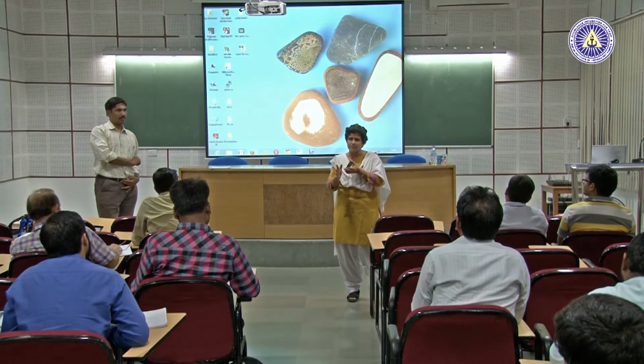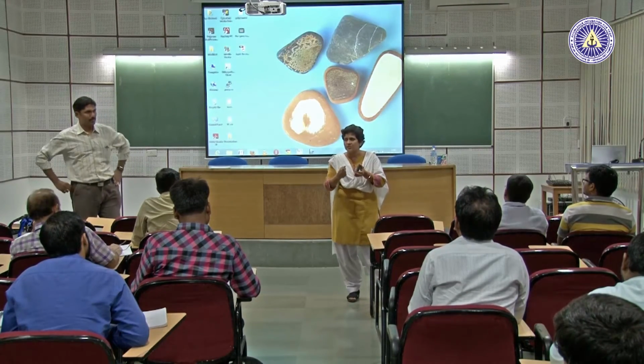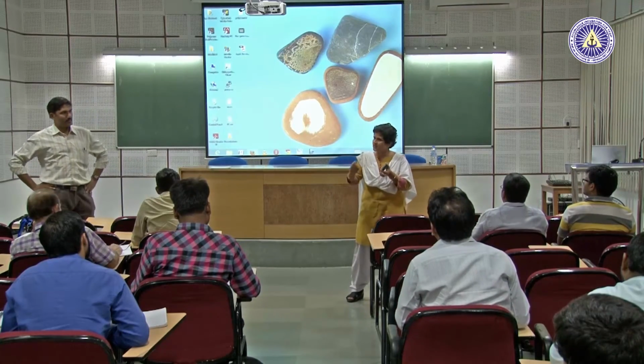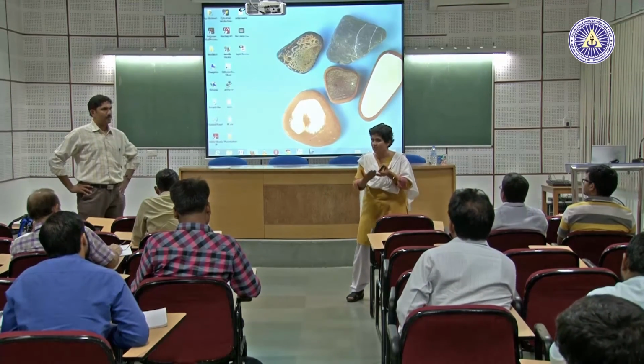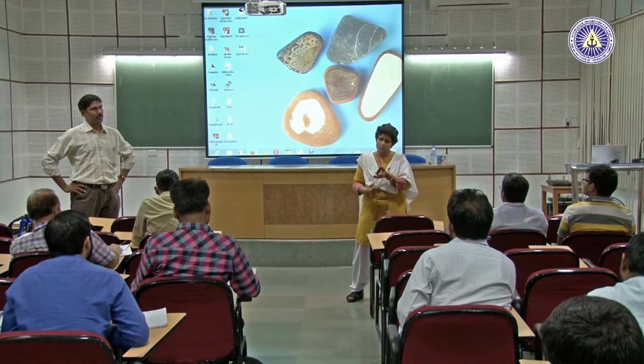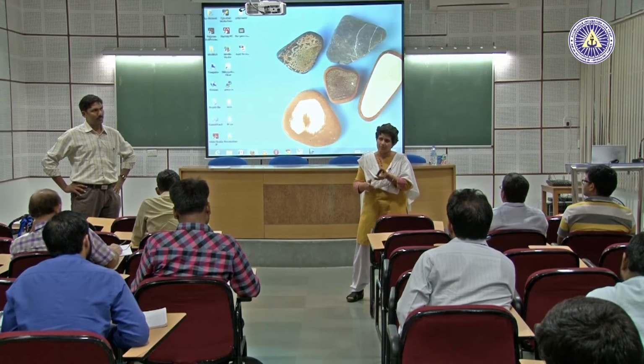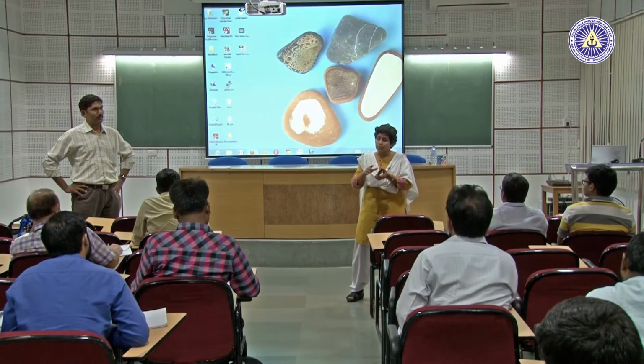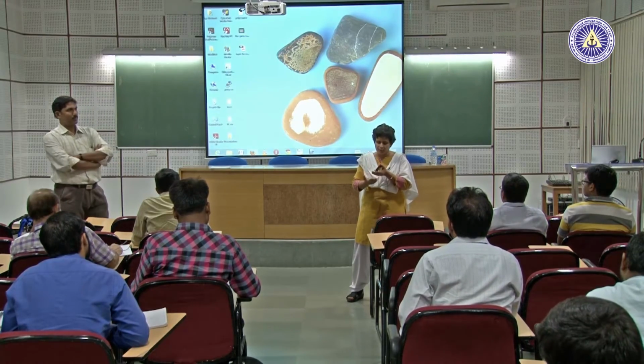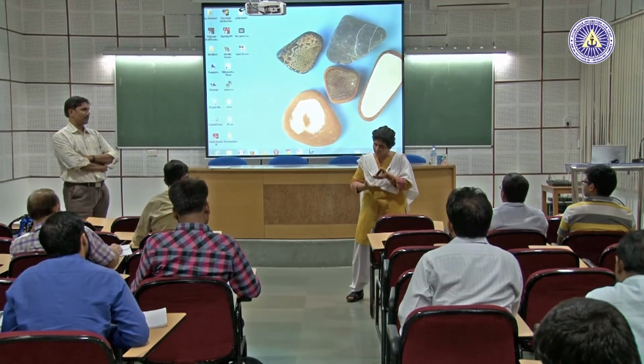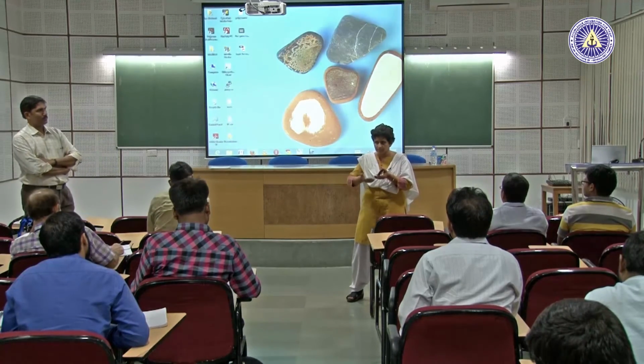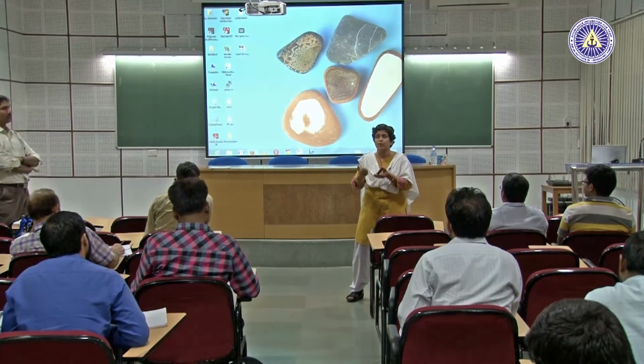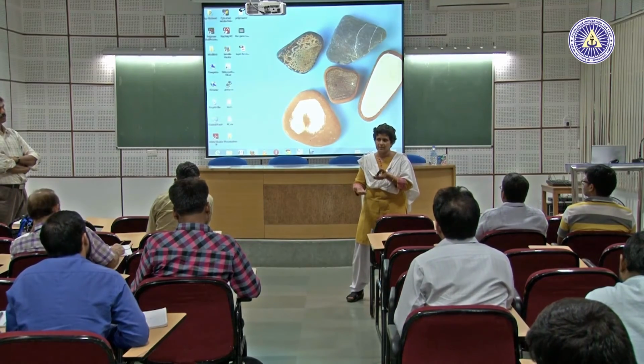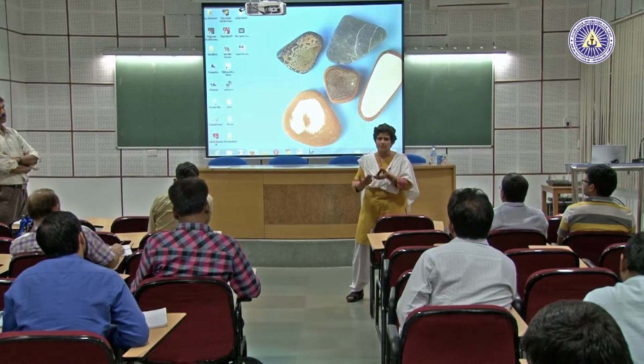So you can make a film, but it may not be very good. I mean, they do scratch tests, right? If a film doesn't have good adhesion, it will scratch easily. If it has good adhesion to the surface and forms strong primary bonds, then it will be better. So you need to choose the material and the film very carefully. You do have ways out of it. Suppose your film is not compatible with the substrate, you can make a buffer film. You can put a film in between. For example, gold doesn't stick to glass, but if you put titanium in between, you have a good film.